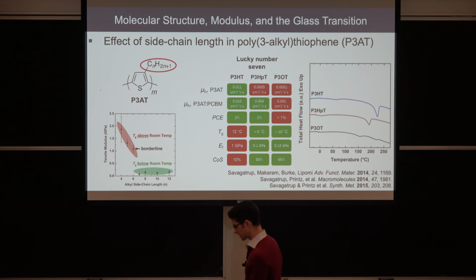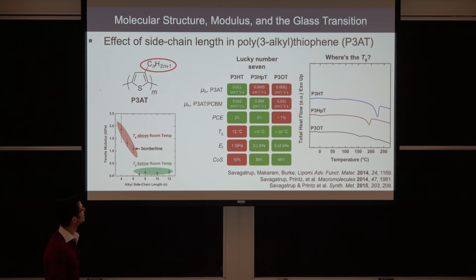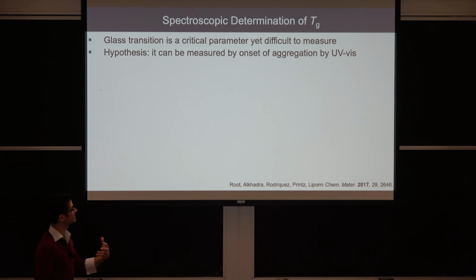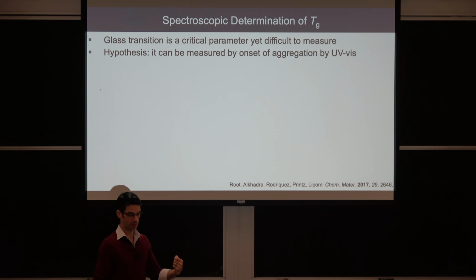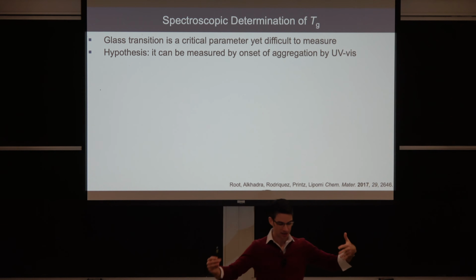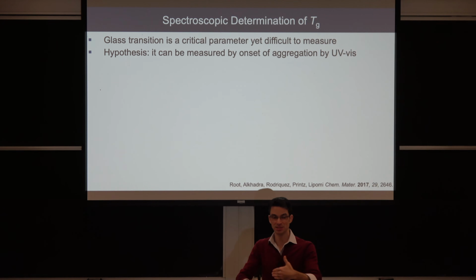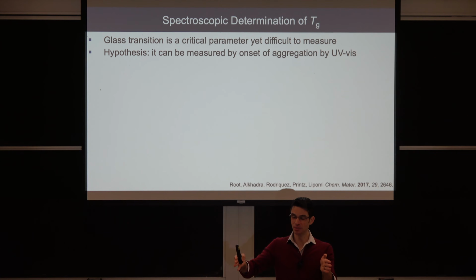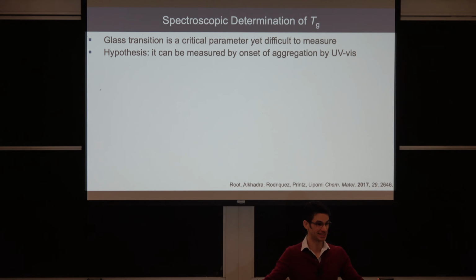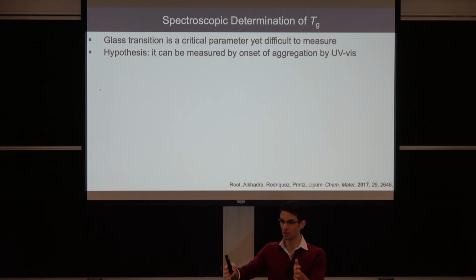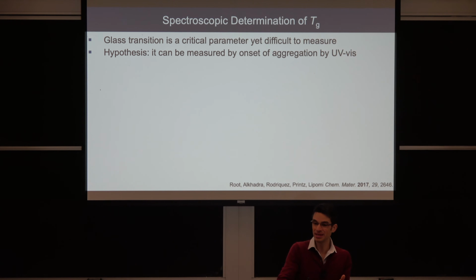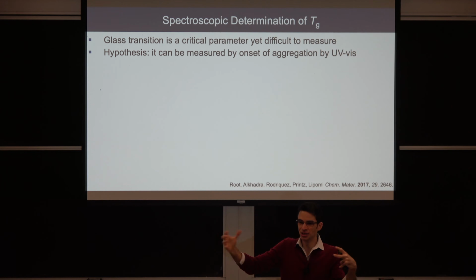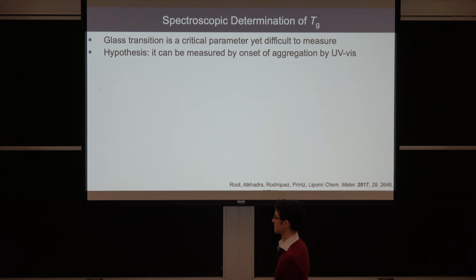So we wanted to come up with an easier method that would give us a really sharp signal. So the question was, where's the Tg? And my students had this hypothesis that it can be measured by the onset of aggregation by UV-vis, ultraviolet visible spectroscopy. Now, what is the onset of aggregation? Who cares about that? Well, a conjugated polymer will pi stack. So these pi orbitals will stack up and form a new type of absorber in the solid state. So these little crystallites of the semiconducting polymer will absorb differently. And if we can measure the temperature at which these crystallites form, that means that the amorphous chains have enough energy to form these crystallites, and we hypothesize that that would be equivalent to the glass transition temperature.